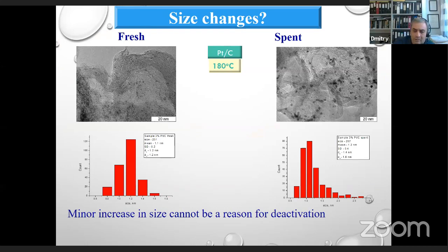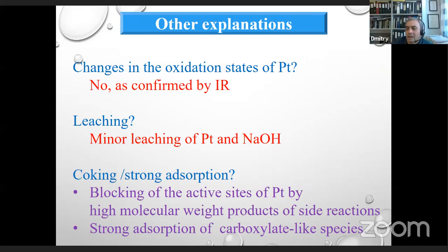One option certainly could have been sintering, but that was apparently not the case, since only a minor increase in the size was observed when we compare the fresh and spent catalyst. So a minor increase in size certainly cannot be a reason for deactivation. Could that be changes then in the oxidation state of platinum? No, as we confirmed by infrared. Could it be because of leaching? The answer is also no, since we have observed only minor leaching of platinum and sodium hydroxide.